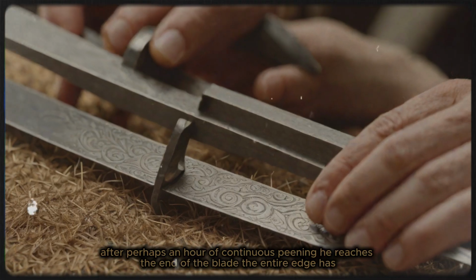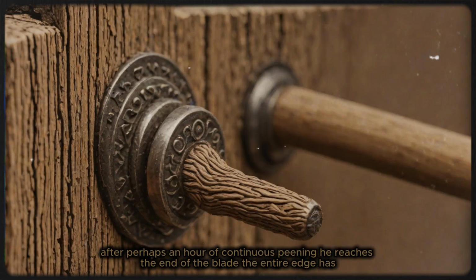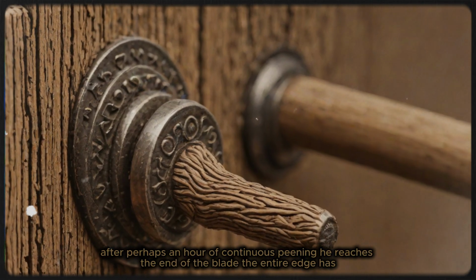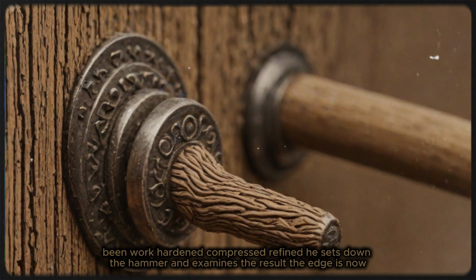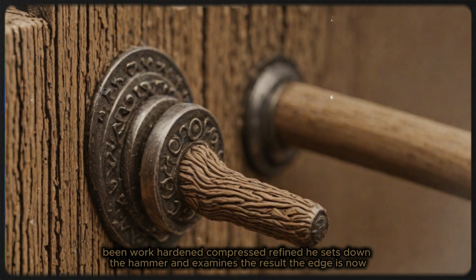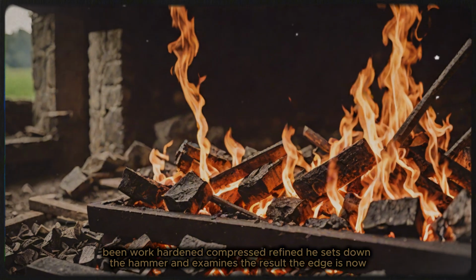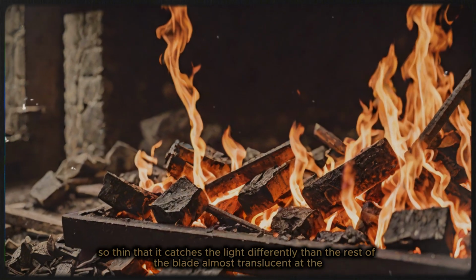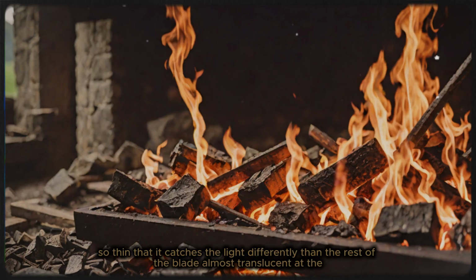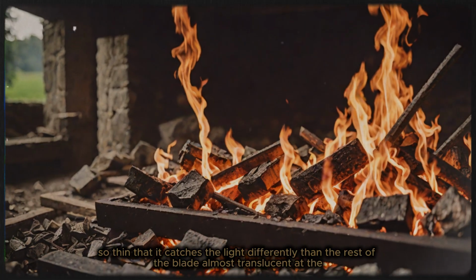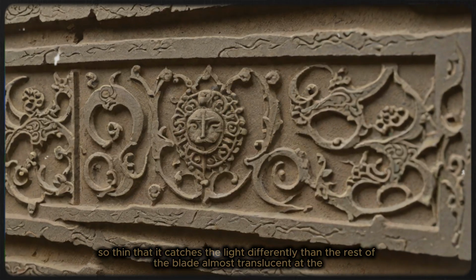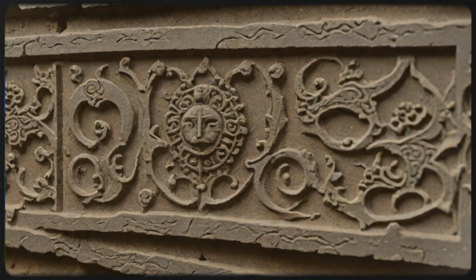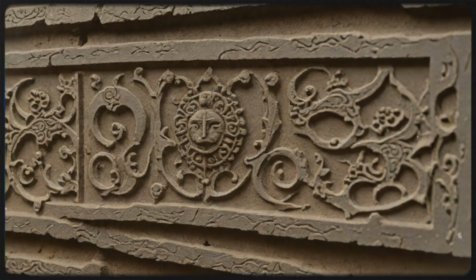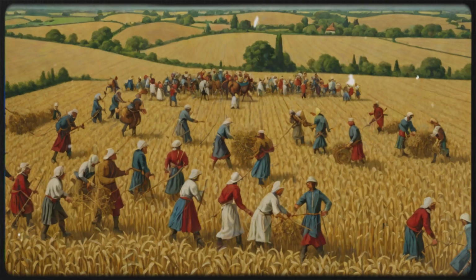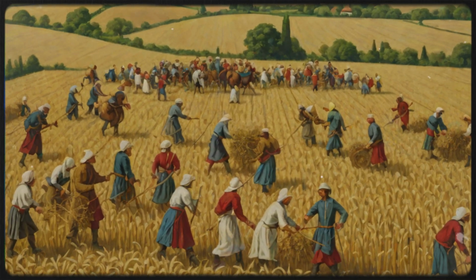After perhaps an hour of continuous peening, he reaches the end of the blade. The entire edge has been work-hardened, compressed, refined. He sets down the hammer and examines the result. The edge is now so thin that it catches the light differently than the rest of the blade, almost translucent at the very edge. He tests it carefully with a piece of grass from outside, holding the stem against the edge and pulling gently. The grass separates with almost no resistance, sliced cleanly through.